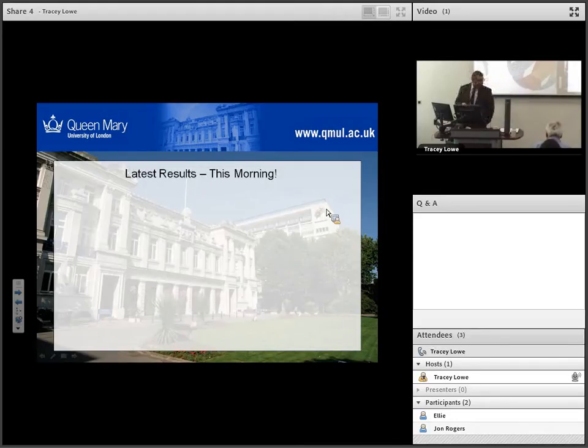And the results I got this morning, which is why I wanted to put this in, show actually we can now - my students just produced some of these things essentially with very minimal cracking. So by using this sequential technique, we can start to get these really quite dense but rough perovskite films on the surface - this is on FTO, so we need to do this on zinc oxide.